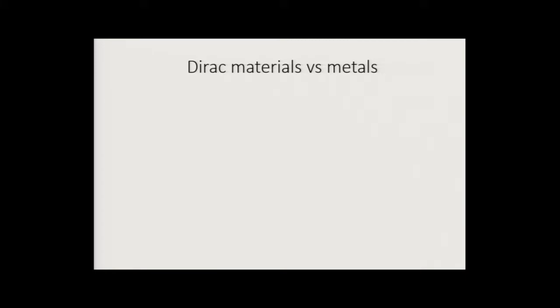All right, so let me build up a little better classification, or try to tell you what the differentiator is. Take a metal. You have a three-dimensional band structure. You have energy as a function of three momenta, kx, ky, kz. And if it's a metal, I ask the computer to find the locus of points where the energy for a particle-hole excitation is 0. So if I have three parameters for the function, I quench one with one constraint that energy should be 0. For the three-dimensional system, I will generically have a surface, which is named the Fermi surface in the metal, hence the name.